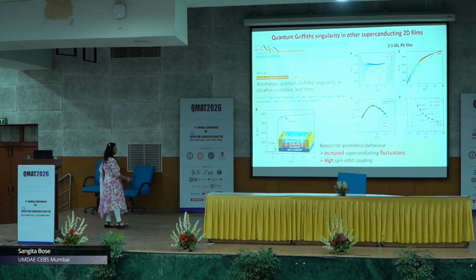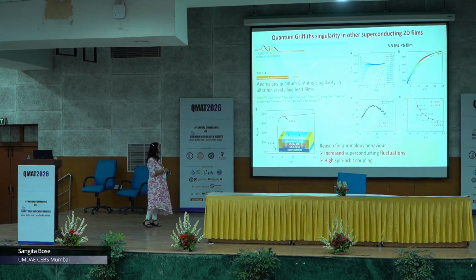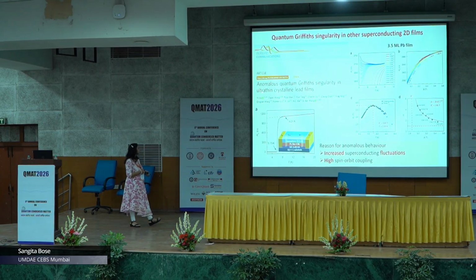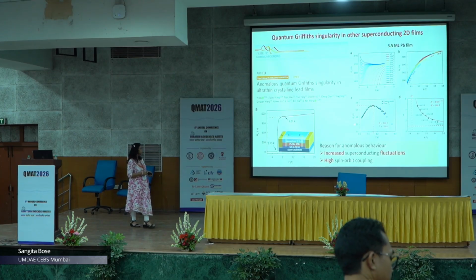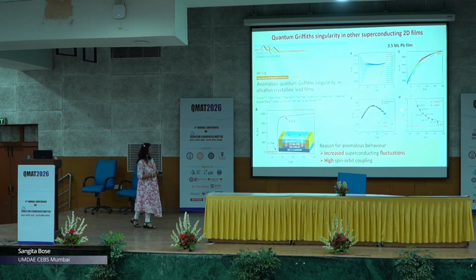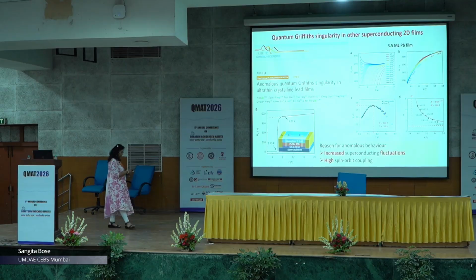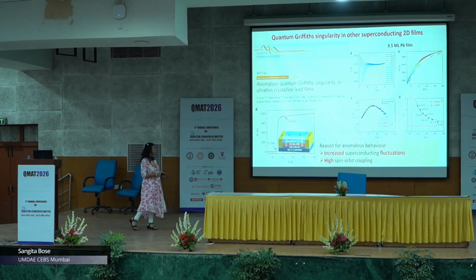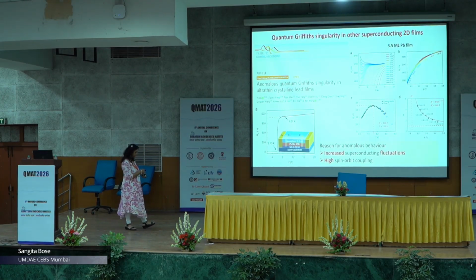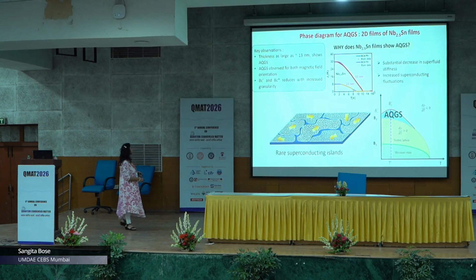Then, when we were actually wondering about our anomalous behavior, we saw this paper which had appeared, and this was also reporting an anomalous quantum Griffiths singularity in ultrathin crystalline lead films. If I highlight their behavior, they also saw a magnetic field tuned superconductor-insulator transition, they saw multiple crossing points, and they saw this divergence of the critical exponent, and they also saw this non-monotonic variation of the critical field. The reason for the anomalous behavior given in this paper is attributed to increased superconducting fluctuations and the high spin orbit coupling in this system. Of course, when we try to reason our things, we have already shown you our measurements of the superfluid stiffness.